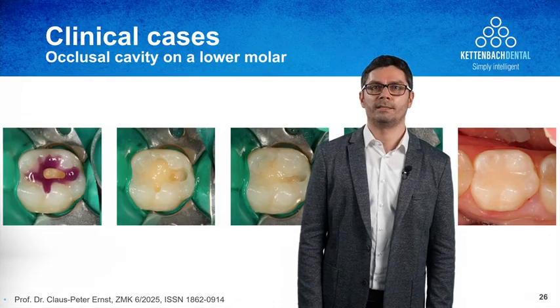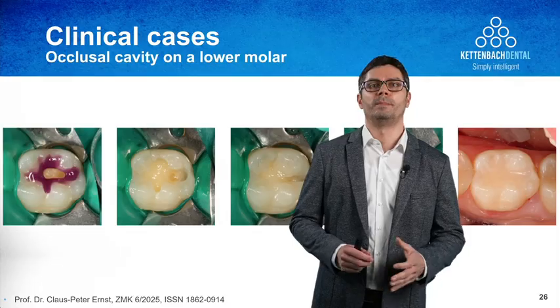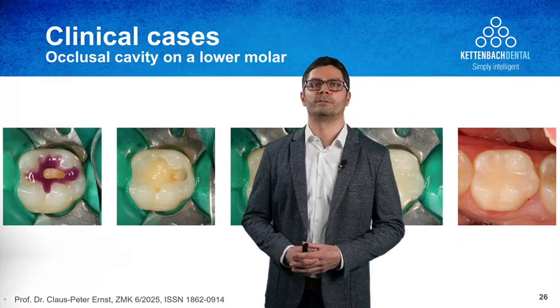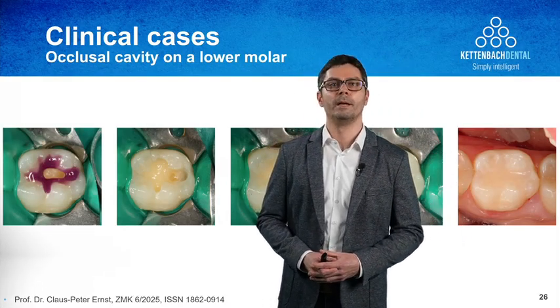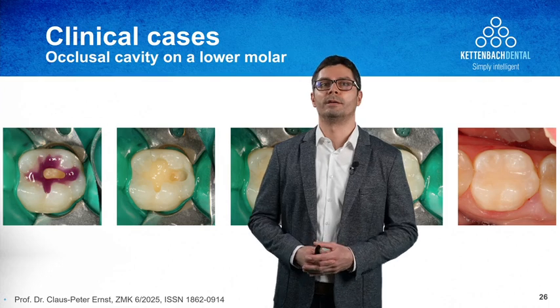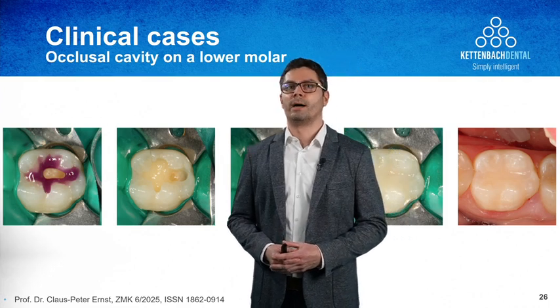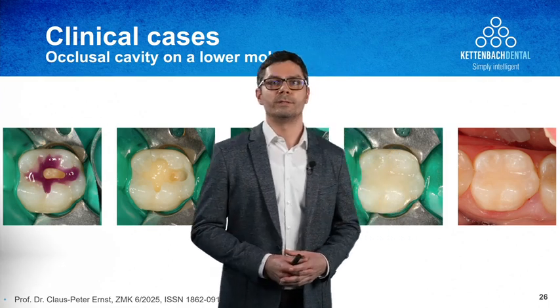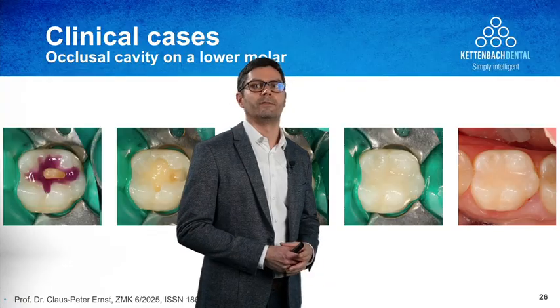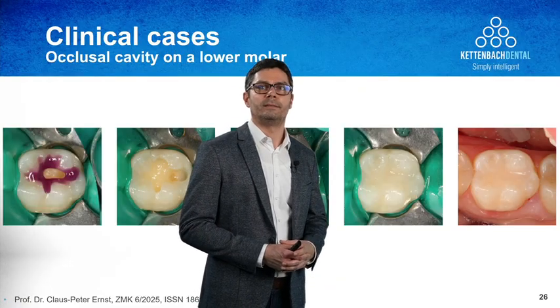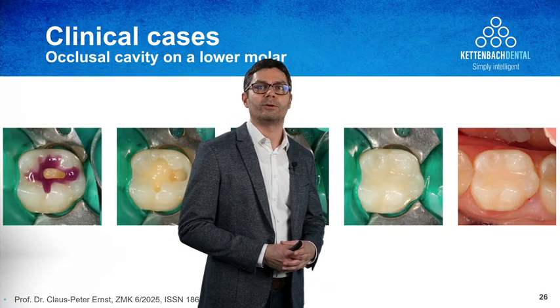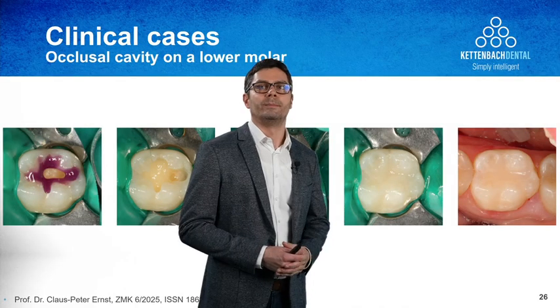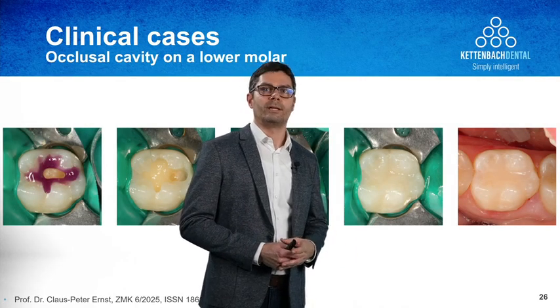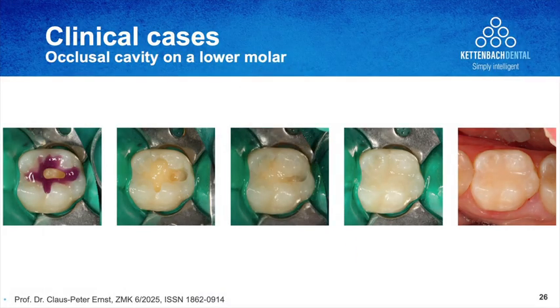One last case that I wanted to show you here is a deeper cavity that was also filled with Visalys Bulk Flow. So you really need the 4mm of polymerization depth. After filling the material, you can see once again a very nice appearance of our material. And you can see this restoration here has a very large occlusal part, so very high in wear in general, but it fulfills all the requirements to achieve this restoration as well.